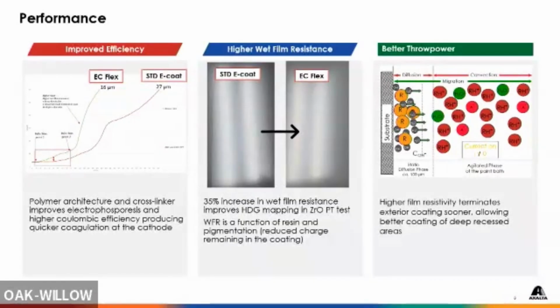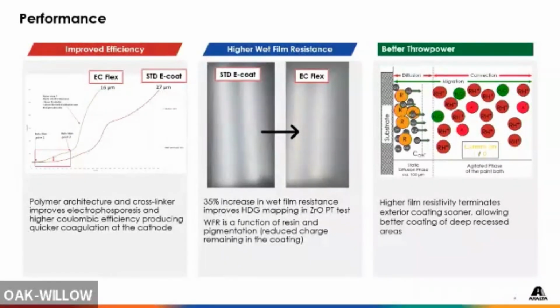And as you can see, the standard Ecoat, because of its wet film resistance, its flow mechanics, does not do a good job of covering over some of that chemical etching in the steel. When we go to the AquaEC Flex, again, because of its coagulation, its wet film resistance, it's able to cover some of that imperfection in the metal a lot better. So that's about a 35% increase in wet film resistance, which is huge for the industry.